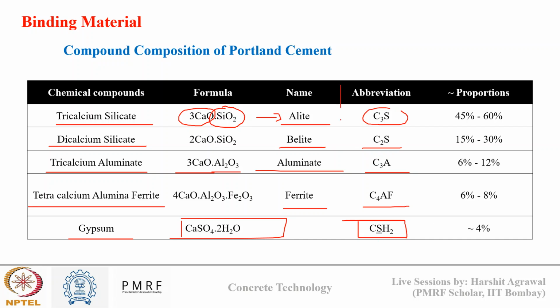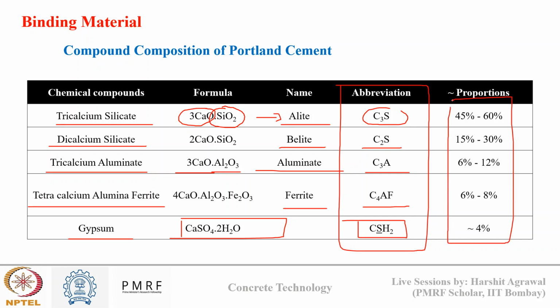The proportion of these final solid solutions in cement is in this range: 45 to 60% is C3S, 15 to 30% is C2S, 6 to 12% is C3A, 6 to 8% is C4AF, and approximately 4% or less is gypsum. This composition differs for different types of cement, and this is the main part that we need to remember when we later talk about hydration of cement.